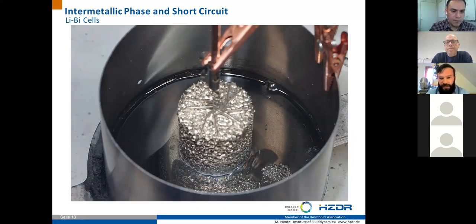That's one problem here. We only heat from below, which means there's a very large temperature gradient. On top, at the lithium-infused foam, there is a temperature several hundred degrees Celsius lower than in the liquid electrolyte. The good point is that the metals have a high heat conductivity, which means everything will melt quite fast, but there is not a good temperature distribution inside these cells. This is also something that will be improved with the closed cells, because then we can heat from the top and the sides as well and have a much better distribution. Thank you.